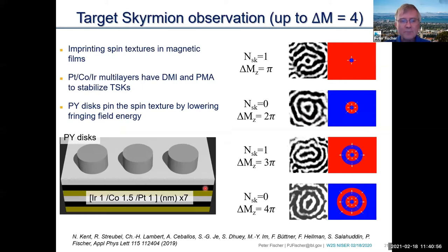What we did is we had a magnetic multilayer of platinum, asymmetric with iridium on top, a nanometer, which we knew has a strong DMI as well as PMA, and it stabilizes skyrmions. We knew this before. Then we put on top of this, by nanofabrication, permalloy discs, which we knew from previous studies would be just in a vortex state. So this is an in-plane structure. What happens if you combine this in-plane vortex configuration with this out-of-plane skyrmion-like DMI structure? What would it look like?